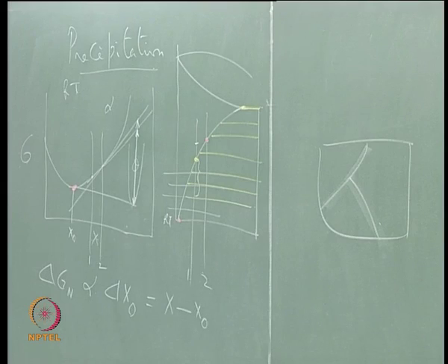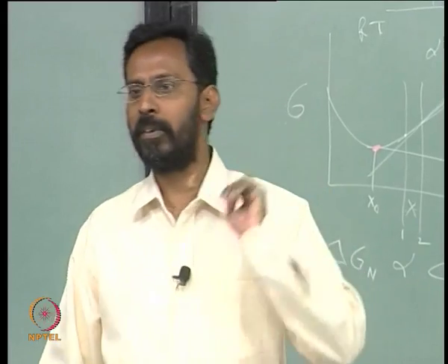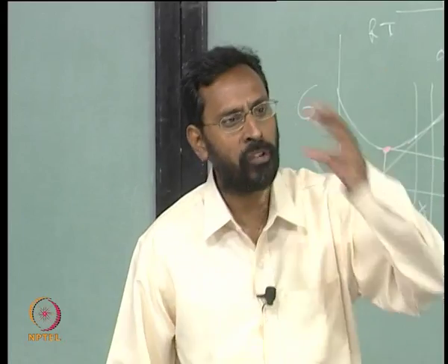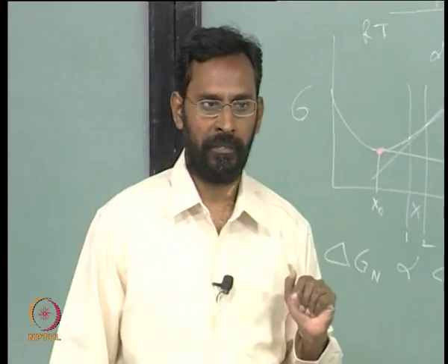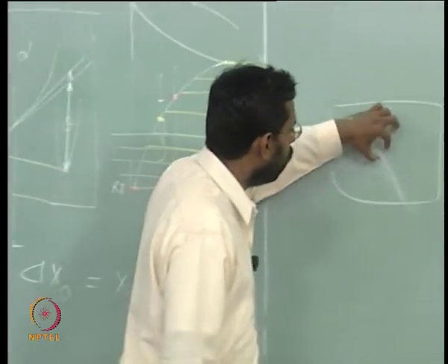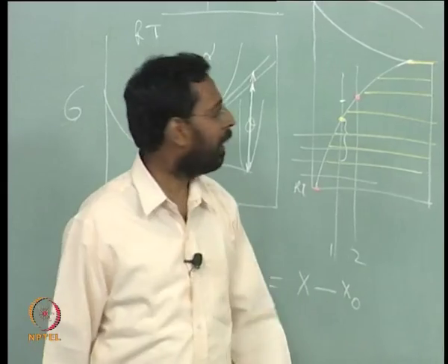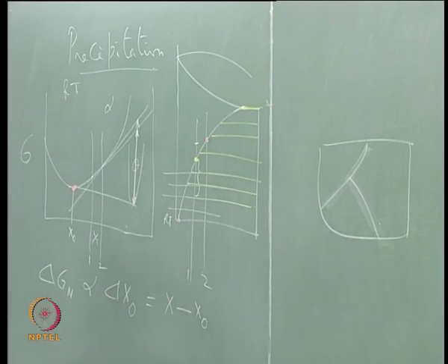So, in such an alloy, you still have age hardening taking place, you will still have precipitation taking place, but in addition to the precipitates you will also have the theta which has been formed during solidification at the grain boundaries. So, you would still have some theta at the grain boundaries, and in fact this theta, how did this theta form? Can somebody tell me, during solidification?